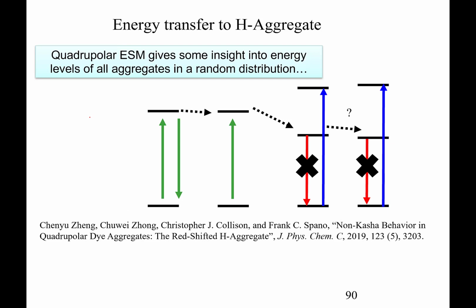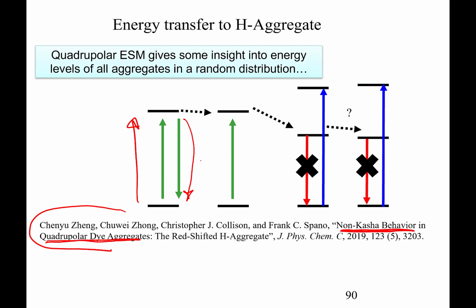Some work that we also recently published from 2019 tells us about the non-Kasha behavior in these very unusual quadrupolar dye aggregates. Very interesting molecules, these Squaraines are. So of course we can get excitation, we can get fluorescence in these Squaraines in the monomers, we can get energy transfer. I showed this earlier. As the fluorescence comes down, then the absorbance can go up.